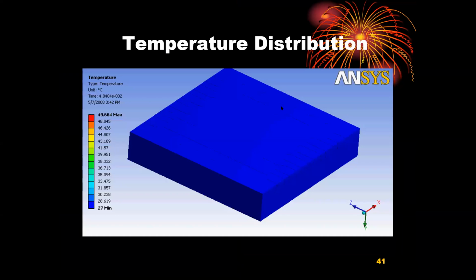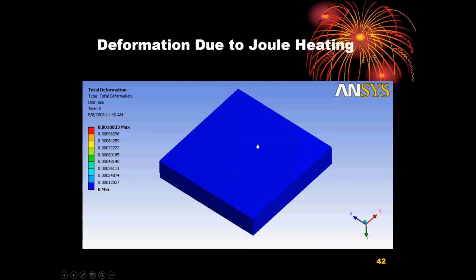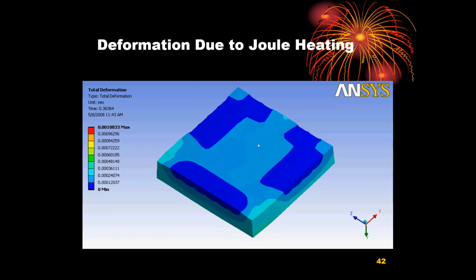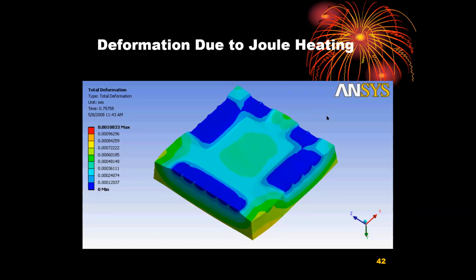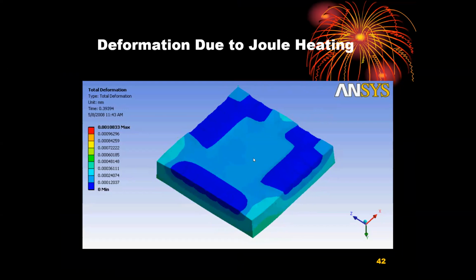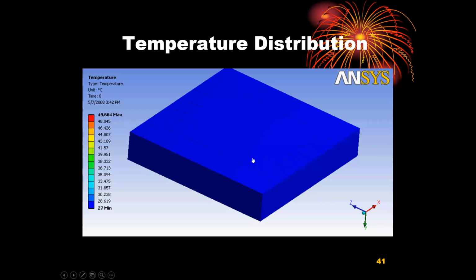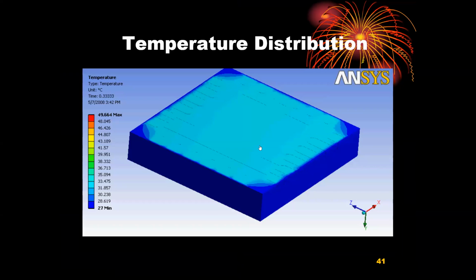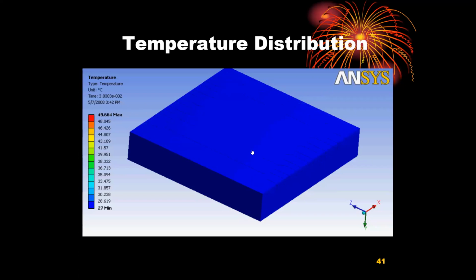The temperature distribution and deformation simulations are shown here, where you see maximum deformation occurring in the encapsulation area, not near the pin. The deformation is pretty controlled here. Coming to the temperature distribution, we see for a particular IC where the maximum operating temperature is about 50 degrees Celsius, the maximum temperature is near the pin, copper lead frame, and the die attached, as I showed you earlier in the 2D analysis.